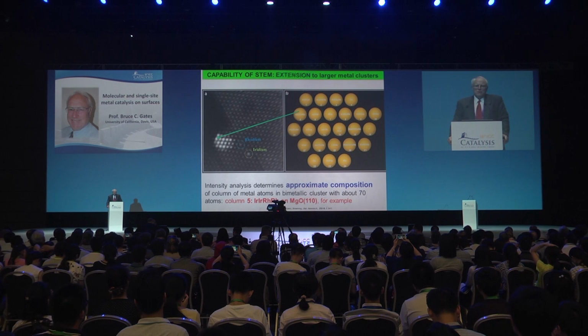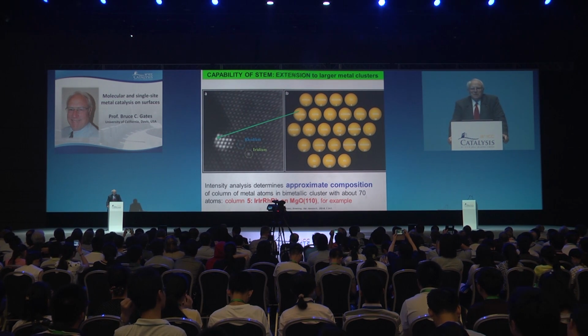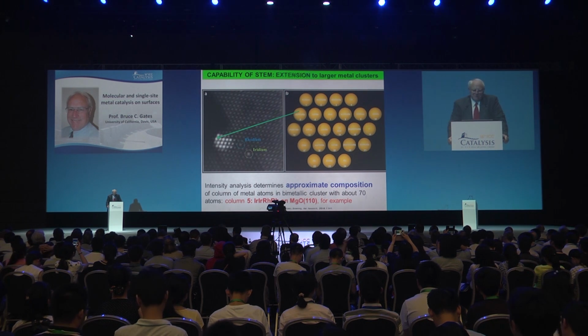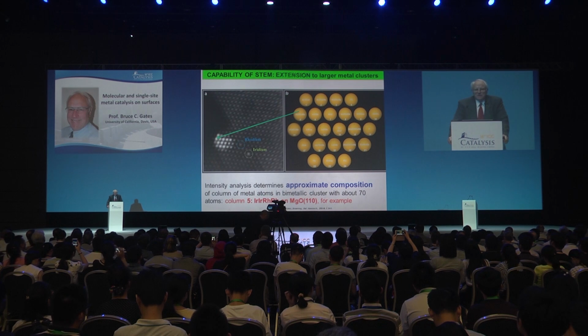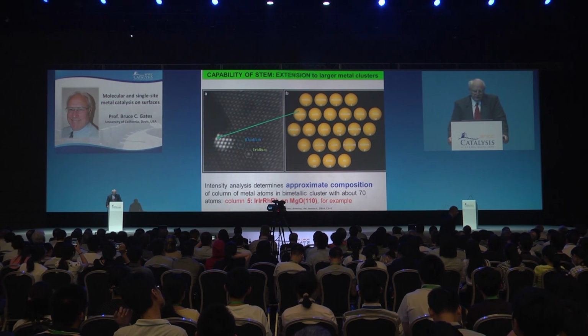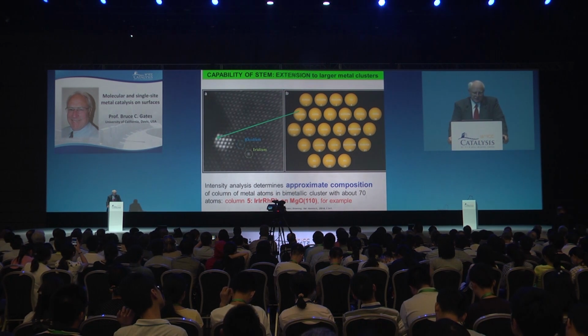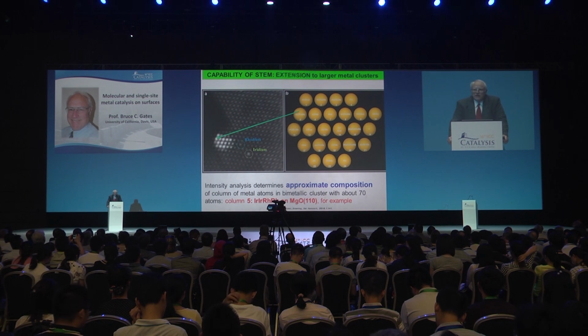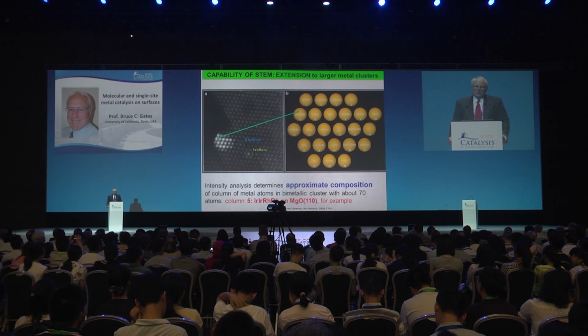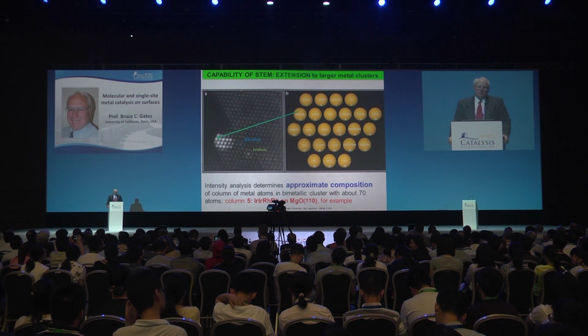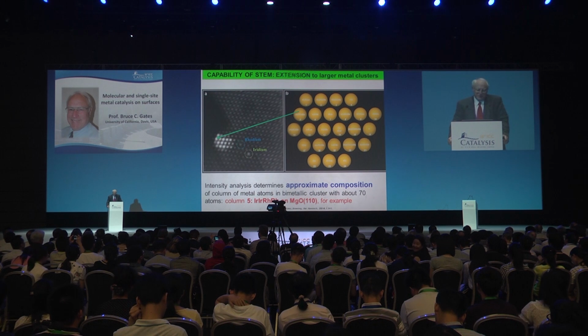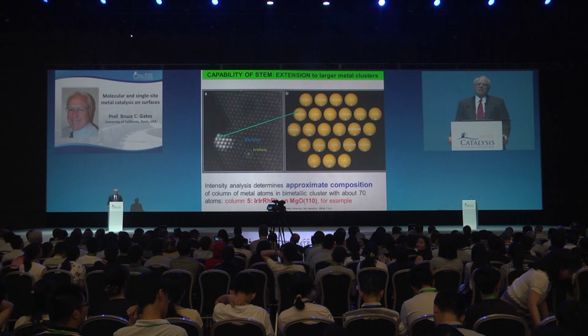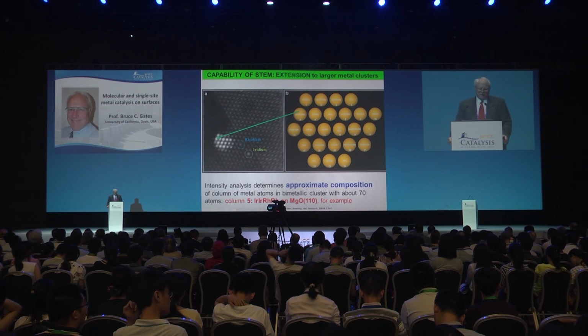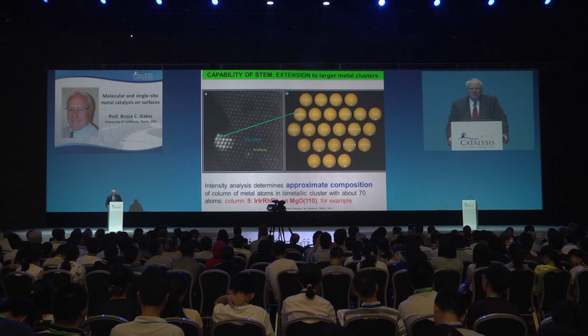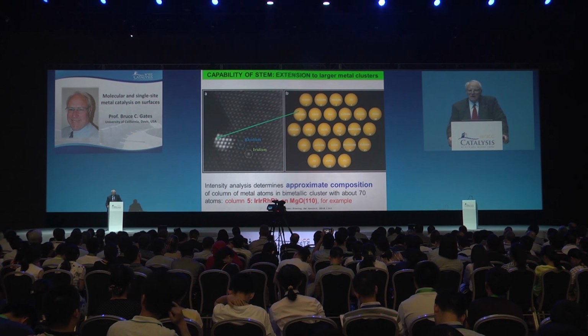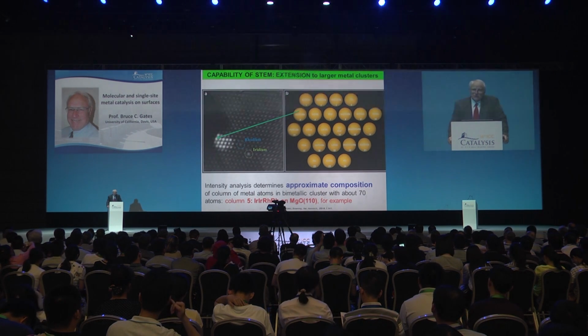One is, let's go back to the microscopy and examine the capabilities of the microscopy. Here's some work with a cluster, at least approximately a 70 atom cluster, a bimetallic. This work could not have been done successfully with a monometallic, in which very careful intensity analysis of the images with the cluster on this very convenient 110 face of MgO allows estimates, and it's a lot of statistical work in this characterization, estimates that provide at least good models of how many metal atoms are in each column that's being examined in the image and what they are.